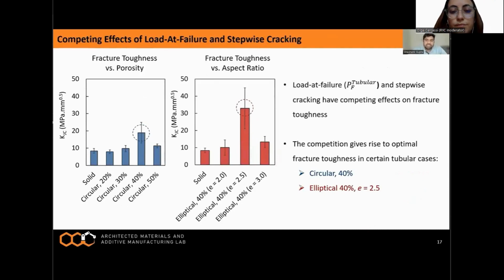If you look at the broader range of the tube size and shape, the competing effect of load at failure and the stepwise cracking gives rise to optimal fracture toughness in certain cases. For instance, among the circular cases, the porosity of 40% exhibits the best fracture toughness, as shown by the blue dots. On the other hand, among the elliptical cases, the porosity of 40% and aspect ratio of 2.5 exhibits the highest fracture toughness, as indicated by this red dot as well.